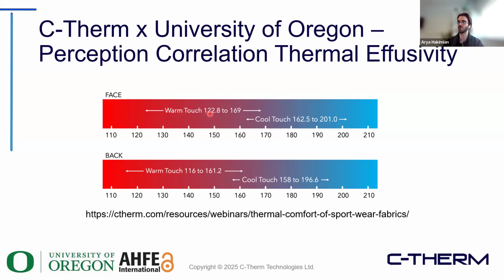So you could generally show that anything definitely below 100, but up to anywhere from about 122.8 on the effusivity to about 169 was considered by many warm feeling. Of course, there's this little gradient in the middle where there's some overlap, but generally speaking, above 162.5 and higher was cool feeling.